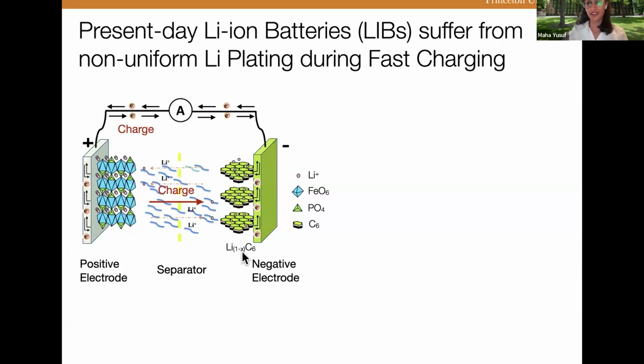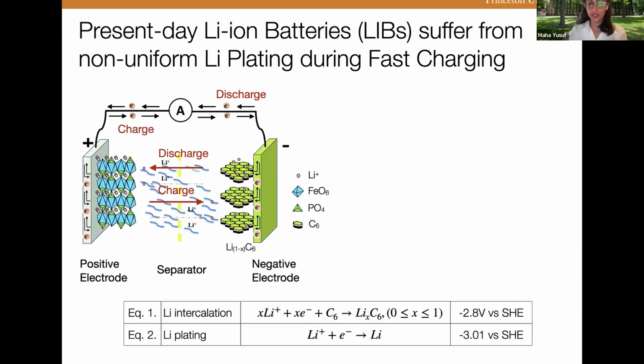Now, when we are discharging the battery, we are moving these lithium ions back from the negative electrode towards the positive electrode. And now when we charge the battery really, really fast, what we are doing is we are moving these lithium ions really fast from the positive towards the negative electrode. And what happens during that process is lithium plating, which is given by equation 2 here, dominates over lithium intercalation, which is what should happen, where lithium gets intercalated between these layers of graphite. And you can look at the electrochemical potentials of the two reactions. They're pretty close to each other. And hence the fast charging creates favorable conditions for lithium plating to dominate over lithium intercalation.